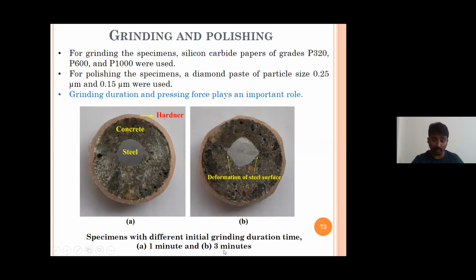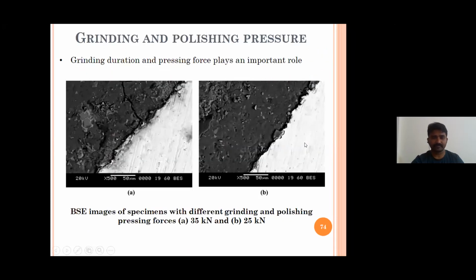If you grind it for more and more, see here, the steel surface is deforming. So I have to restrict my grinding duration to only 1 minute for each of these silicon carbide papers. At P320, I grind for 1 minute, P600 1 minute, P1000 1 minute. After that, I use the diamond paste to clear out a few of the dust particles. So grinding duration, if you observe in those samples in SEM,